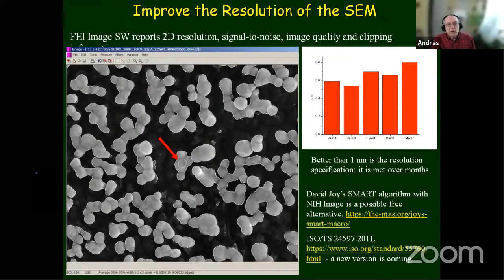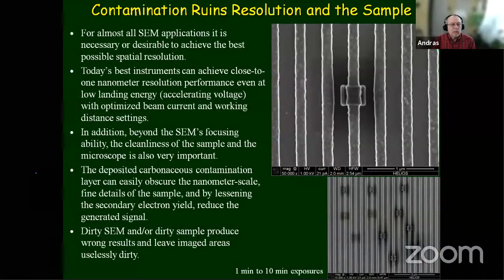So you can see that these red bar results show what performance you can get from an instrument where the specification is better than 1 nanometer. This is at 15 kV. You can see that significantly better than 1 nanometer resolution is possible. We'll talk a little bit later about how important this is. Next slide, please.